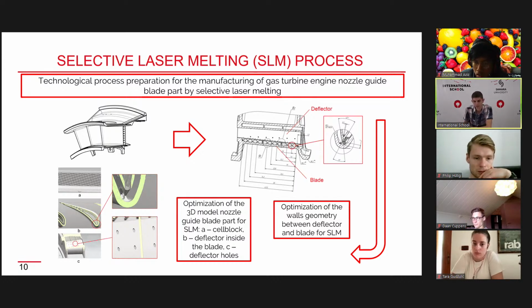So we optimized a 3D model of the nozzle. We put inside here, if it's visible to you, a small cell block. The section of the small tiny cooling channels was also changed, and the deflector was put inside the turbine blade. In traditional technology, it takes too much time, and it's hard to create this blade. Why? Because first, using molding technology, you make the shape of the blade, and separately, you have to make this part called the deflector with small cooling channels, and after that, you put it inside this blade. But here, we made it as one complex single form using 3D printing.